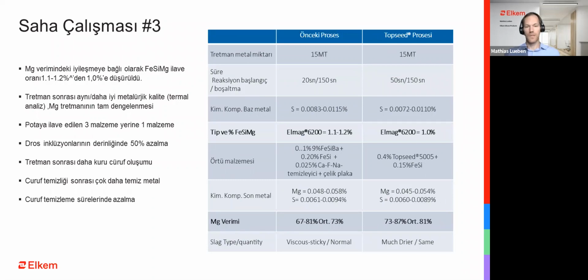Case study number 3. A case study for a big open ladle with 15 metric tons capacity. The reaction start has been postponed a lot from 20 seconds to 50 seconds. There is a smaller reduction in FeSiMg from 1.1 to 1.2% to now 1.0%, thanks to the improvement of the magnesium yield from 73 up to 81%. Same metallurgy after treatment has been achieved with a full offsetting of the influence of the treatment.